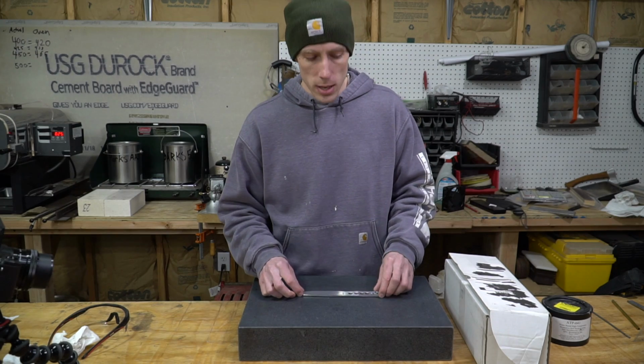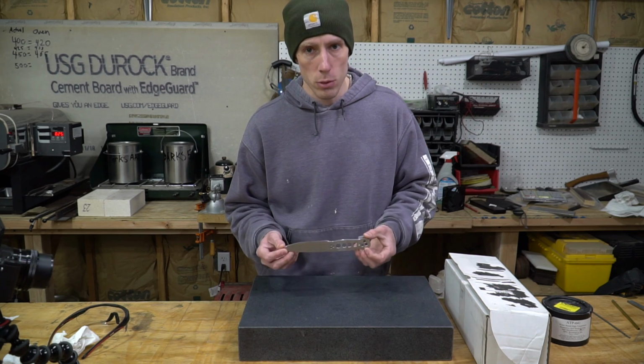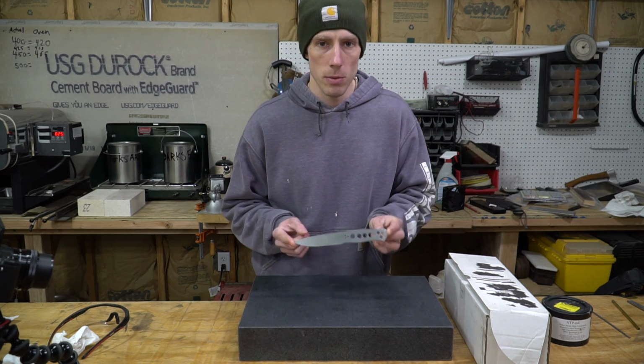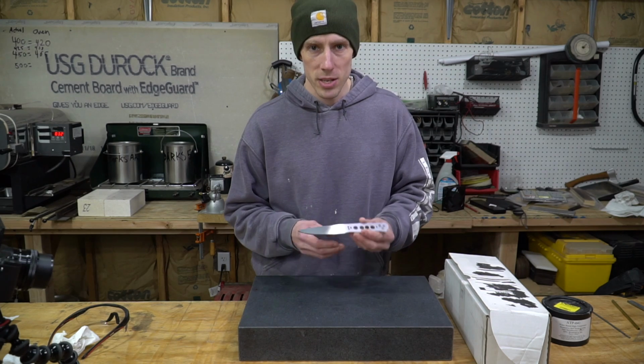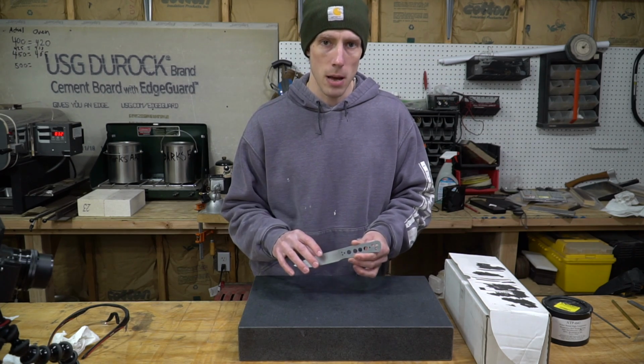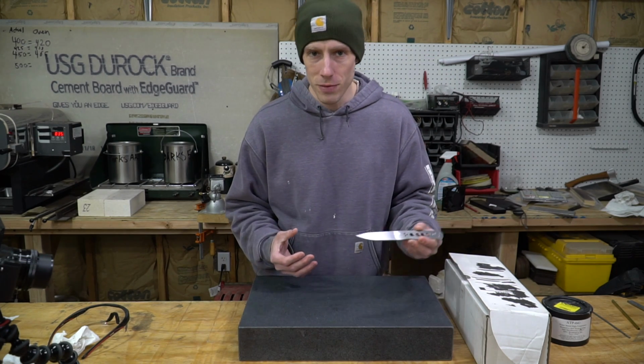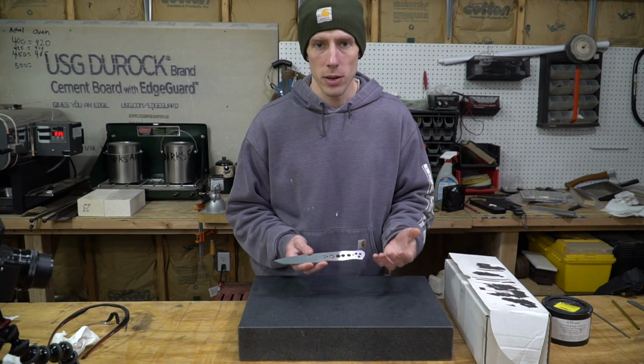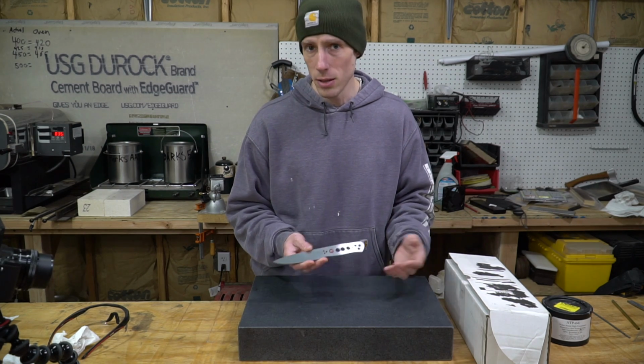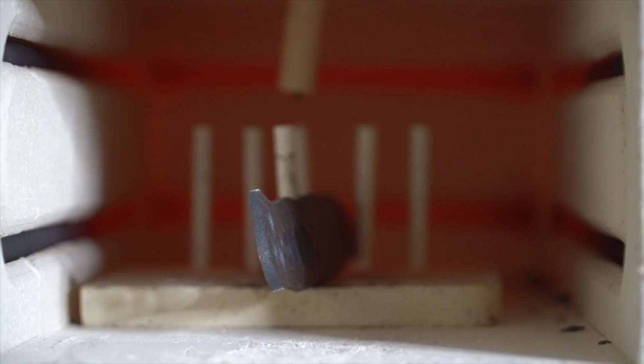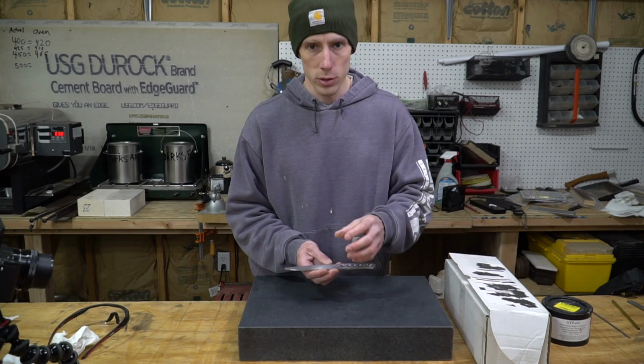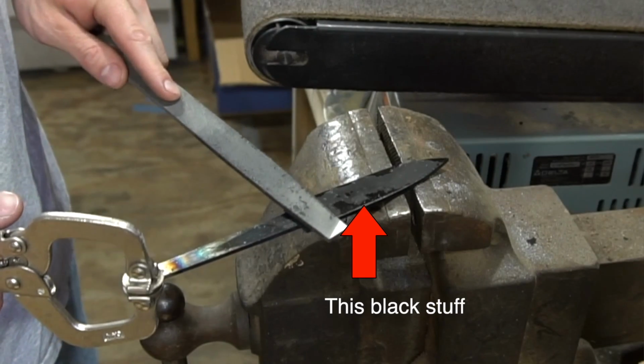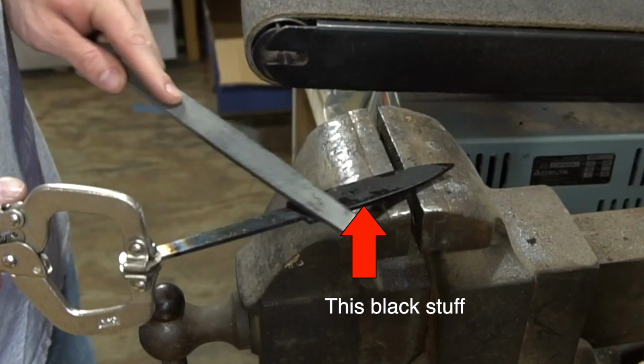So the first thing that we're going to do here is go ahead and do a foil packet for this during the thermal cycles. Now what that's going to do is protect this knife from the oxygen in the atmosphere. A simplified version of this is that as the knife, or as high carbon steel, is exposed to very high temperatures, some of that carbon will actually cook out of the steel and deposit itself on the surface in the form of scale.